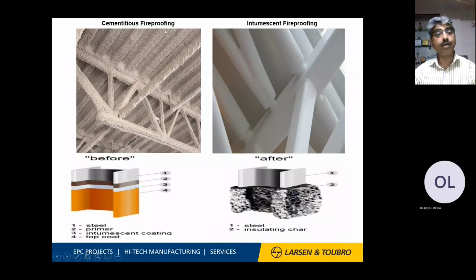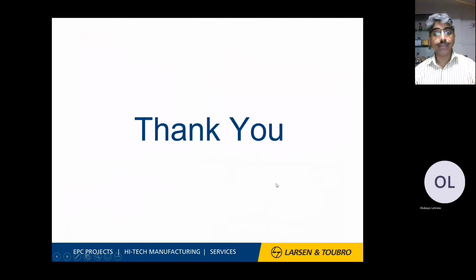This is about the cementitious fireproofing requirements. This is how the coatings are applied. 1, 2, 3, 4 layers: steel surface, primer, intumescent coating and top coats. After fire, you can see it looks like this, it has expanded. So it is protecting the structure so that the temperature won't reach the structure. So this is how it looks after fire.